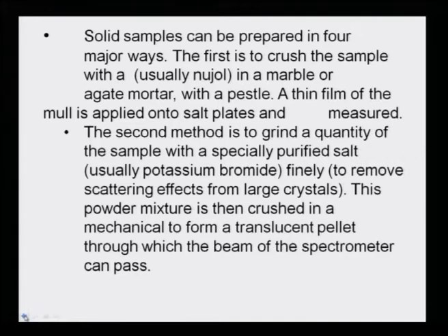A thin film of mull is applied onto salt plates and measured. The second method is to grind a quantity of sample with a specially purified salt, particularly potassium bromide, finely crushed to remove scattering effects of the large crystals. This powder mixture is then crushed in a mechanical press to form a translucent pellet through which the beam of